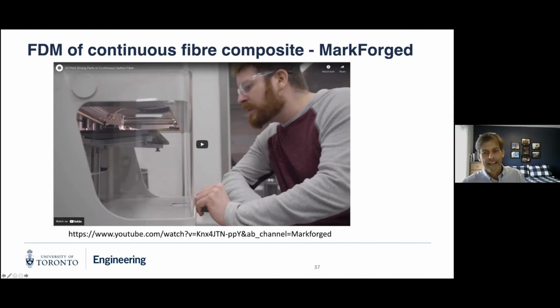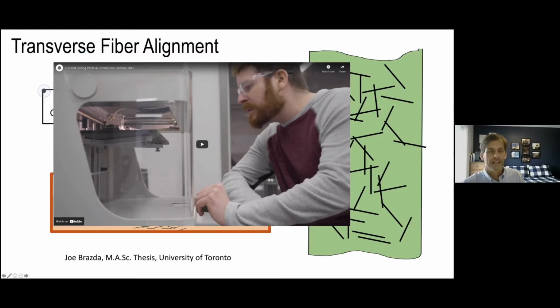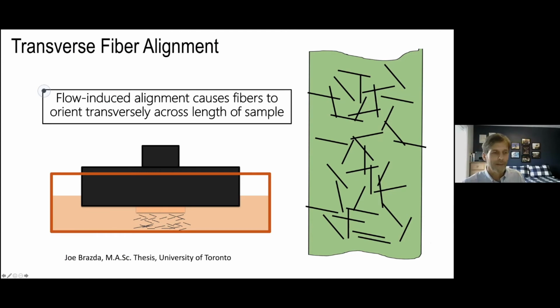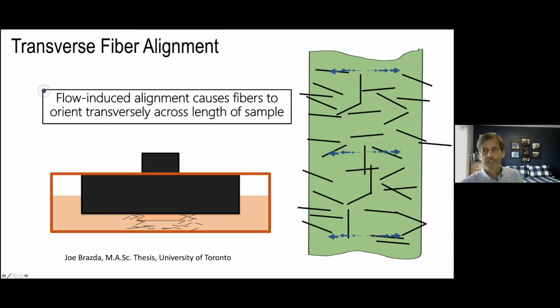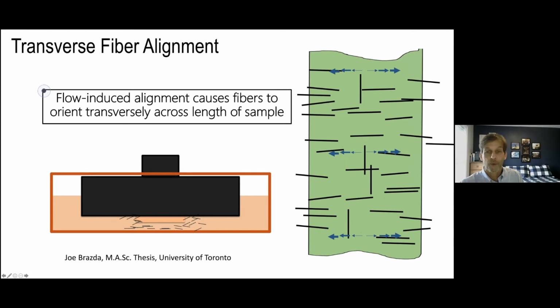And just another little bit of research that I've done. I was interested in seeing whether in inverted stereolithography we could add fibers. So I had a master's student work on this. We were trying to print a long specimen. We want the fibers lined up in the vertical direction, in the long direction. So we bring the build plate down when the specimen is partly built. And what do we see? The material gets squeezed out sideways, and actually the fibers line up in the wrong direction. So it's the opposite of what we wanted.